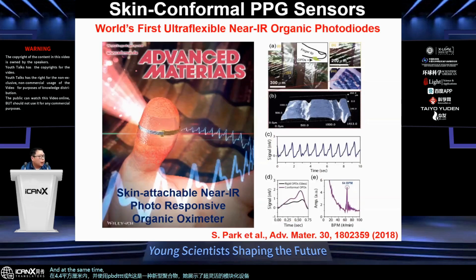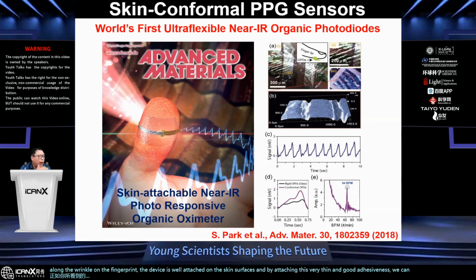At the same time, I demonstrated a slightly different focus, a biomonitoring system using organic optoelectronic devices. This is the first ultra-flexible and near-IR responsive organic photodiode. When the device is attached on the skin surface, as you can see, along the wrinkles of the fingerprint, the devices were attached on the skin, and with this very thin design and good adhesiveness, we can get a high signal-to-noise ratio of the PPG signals.